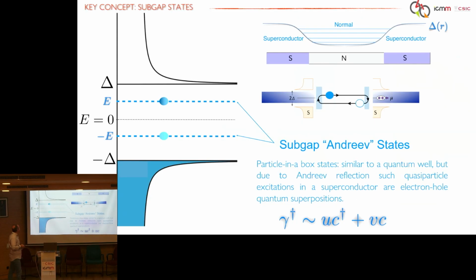All right, so a key concept in these devices is the concept of Andreev states, or subgap states in general. In a standard superconductor, you all know that you have a superconducting gap, but when you have gaps, or in general pairing terms, that are spatially dependent, like in an SNS junction, you can create discrete levels inside the gap of the superconductor. This is like quantum well levels, essentially. These are the discrete levels that you create in a quantum well. The only difference here is that you have this superconducting boundary, and what we call an Andreev reflection: an electron becomes a hole by putting a Cooper pair in the superconductor. And this creates superpositions between electrons and holes. These discrete levels are, and this is important, superpositions between electrons and holes that live inside the gap of the superconductor.